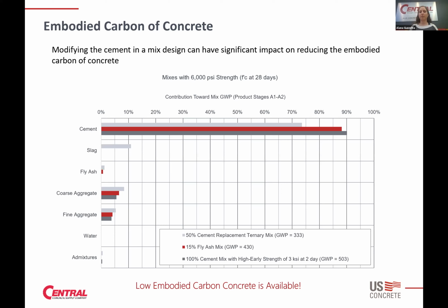And then the red bars are for a 15% fly ash mix. So that means 15% of the cement is replaced with different powder that we call fly ash. That's a byproduct of burning coal, and it's a waste product that would otherwise be put into a landfill. And then the light gray bars are from a 50% cement replacement mix, where we're using a blend of supplementary cementitious materials that Michael talked about.